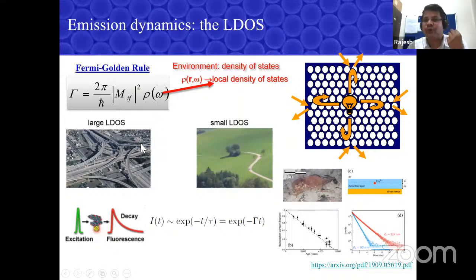For example, if you don't clearly get what LDOS is, a large LDOS means there are a lot of pathways for the light to propagate to the outside world. There are many ways light can take. If the LDOS is reduced, there are only 1 or 2 ways where light can get out of the system. So typically what we do, we take a sample, we excite with a pulse laser, and we measure the decay of the excited emitter. So you look at the intensity of the emitted light, it goes as an exponential, with the term gamma, and gamma is related to the density of photon states.